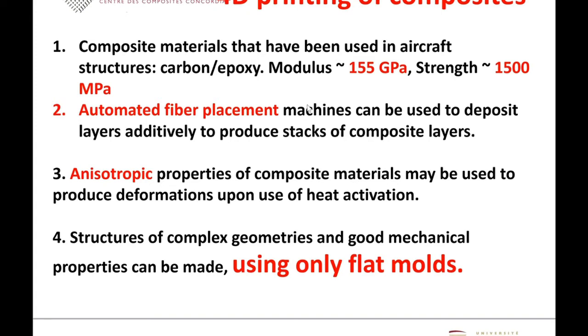The second difference is that we use an automated fiber placement machine, which is a fairly large machine compared to the 3D printer. Normally the 3D printer is fairly small. It can fit onto a desktop, and it can make some kind of small components. But the automated fiber placement machine is a fairly large machine. It can be used to deposit layers additively to produce a stack of composite layers. And these layers consist not only of the resin, but also the fibers. These are continuous fibers. So that's the second difference between the 4D printing of composite and the regular 4D printing.